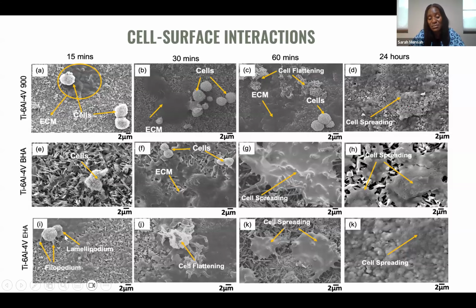But then in cell attachment and growth, there are some features of the cell, the filopodium and lamellipodium, which normally will start to extrude and cause the cells to begin to move. And we saw that as early as 15 minutes. Then at 30 minutes, we could see that the annealed titanium, which was used as a control, was still pretty much spherical. But the coated ones started losing their spherical shape and started spreading on the substrate.